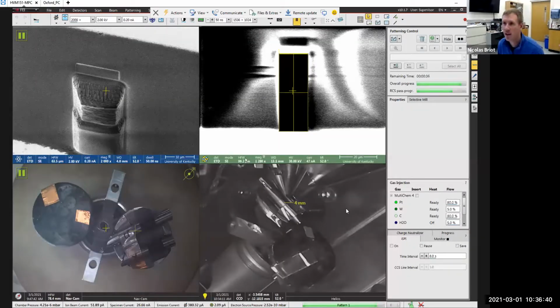You set the cut to run, you just walk away, and then you come back and you have a really large cut. And then you go to the SEM and you have a really big region to play with. So I think that's something we definitely need to use in the future. I mean, we'll get it a month and a half from now. Just know that those things exist too when you are stuck between mechanically polishing and grinding or using a FIB. You have an in-between solution, and that's why we're getting the instrument.